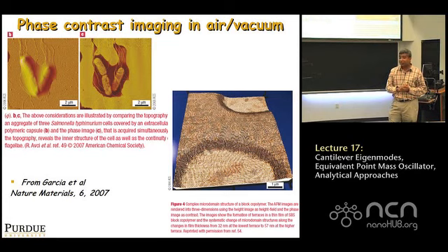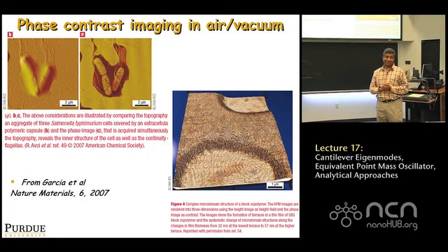Is it energy dissipation? No, it's not, because they haven't plotted sine of the phase lag, right? So you cannot say just by looking at this whether the darker parts are more or less energy dissipation. This is the problem. You see contrast, but to extract the physics, to get an idea where there is more or less, you need to be sure you're dealing with phase lag, and you need to plot sine of phase and so on, okay?